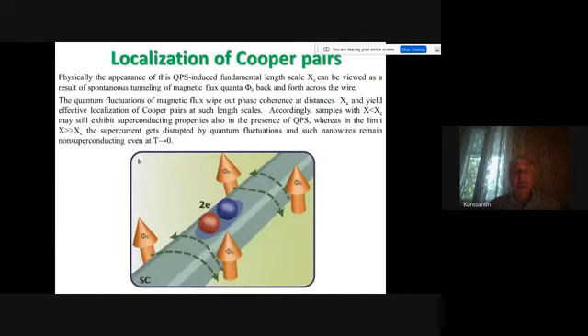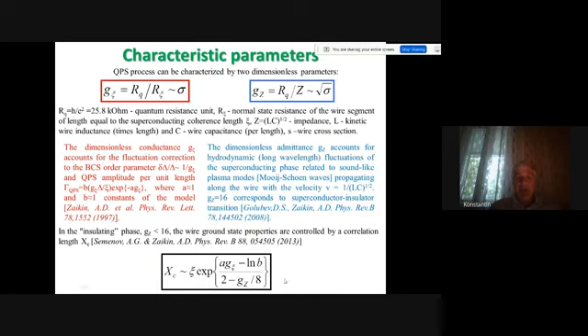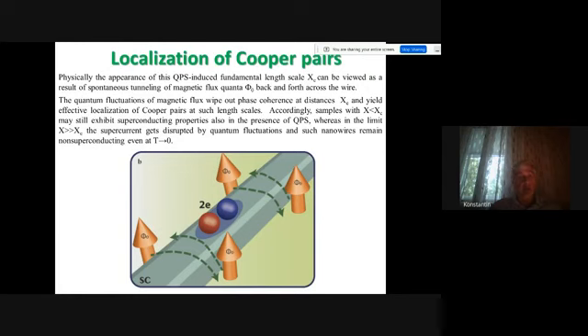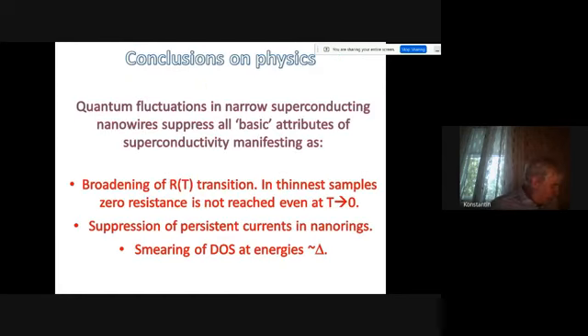So if xi C is much smaller than the length of the wire, then the Cooper pairs are localized and the system cannot show integral superconducting properties. But if the length of the system is smaller than this xi, then the system shows some superconducting properties, like, for example, a superconducting gap with broadened density of states. I again want to stress that this depends exponentially strongly on the cross-section. So just a few nanometers of change in the same nanowire might bring it from one limit to another. So now I conclude on physics.